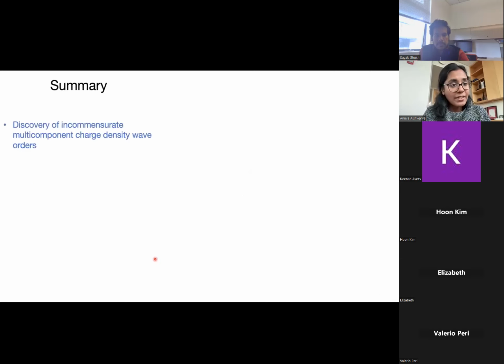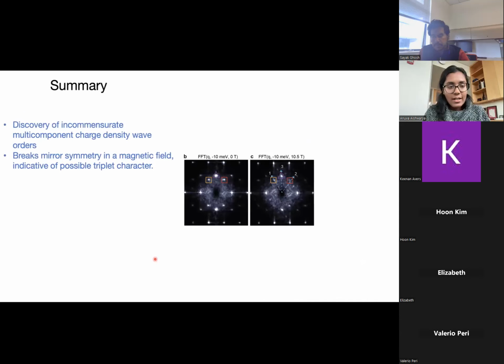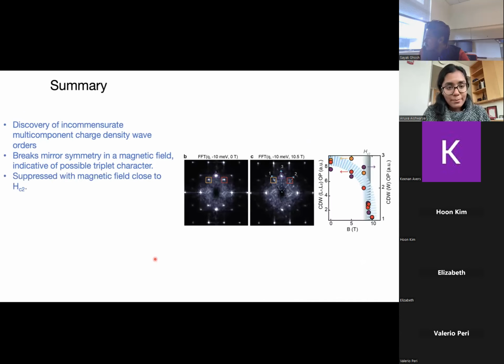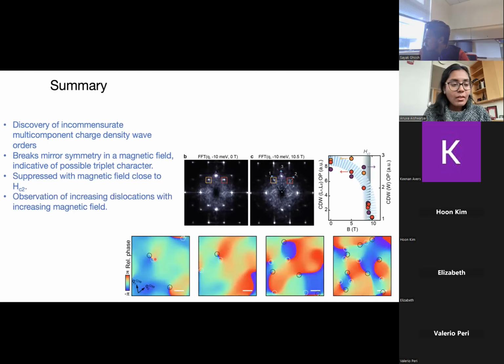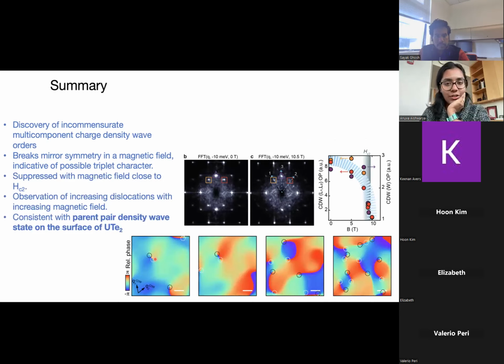So in summary, this work reports the discovery of an incommensurate multi-component CDW in UTe2. The CDW breaks mirror symmetry, indicative of a possible triplet order parameter, and is suppressed by magnetic field. We observe an increasing number of dislocations with increasing magnetic field, which is consistent with the pair density wave state in UTe2. However, there are still some open questions.